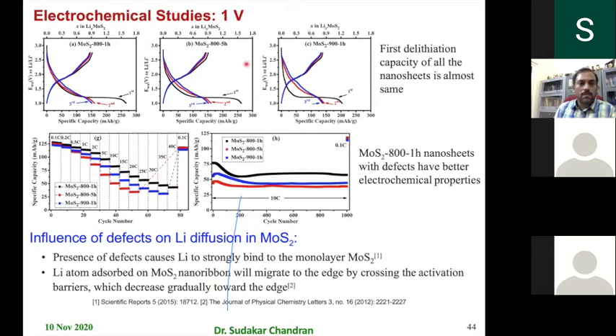Of course, these measurements are done up to 1 volt, where the 1T phase is there. If you go below 1 volt, the Li2S and molybdenum will segregate out. So we wanted to keep it in the molybdenum sulfide MoS2 form itself and then study. That's why the capacity is a little less. But then what we found is the cyclability is much better if you have the defects. Okay, so that's one of the things we found.